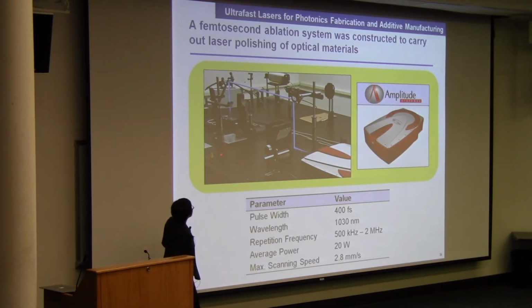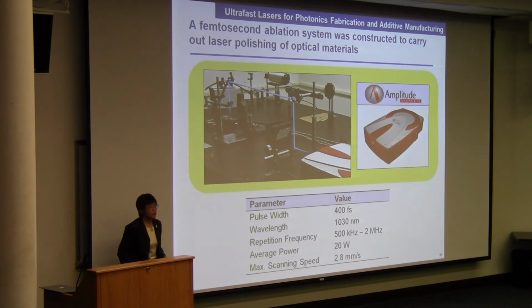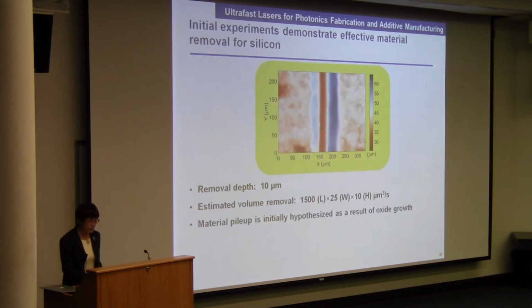This is a 400 femtosecond laser with a wavelength of 1030 nanometers. You can change the repetition rate from 500 kilohertz to 2 megahertz. It has an average power of 20 watts. And we have a computer-controlled translation stage.